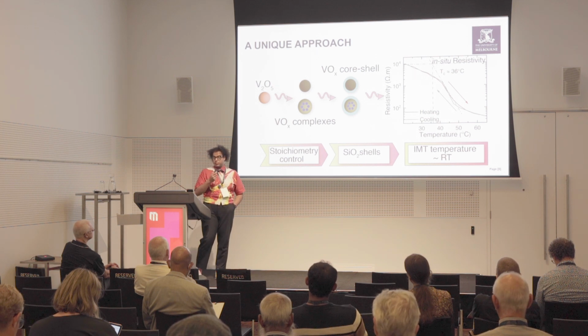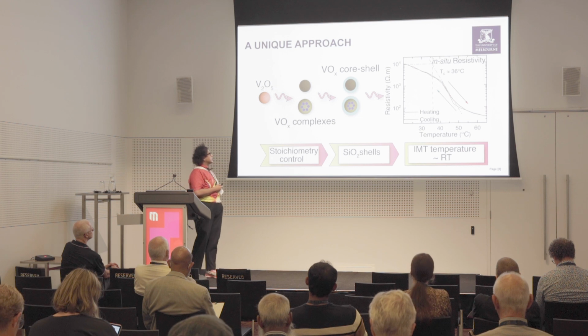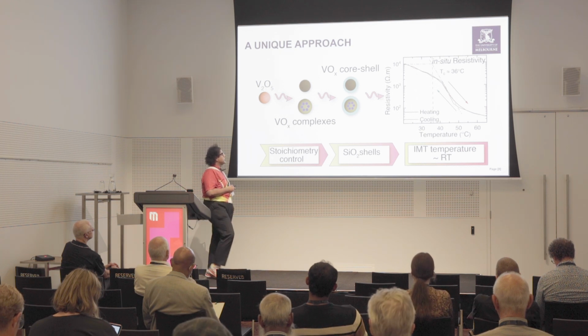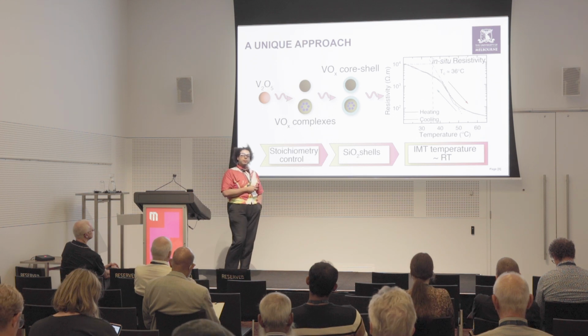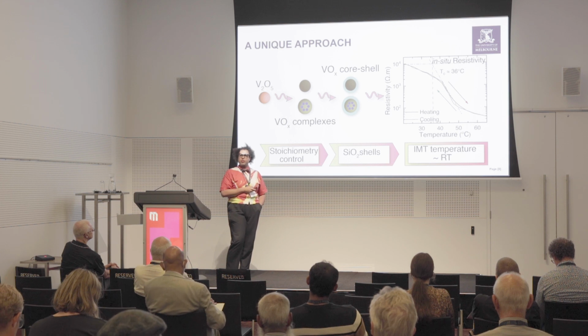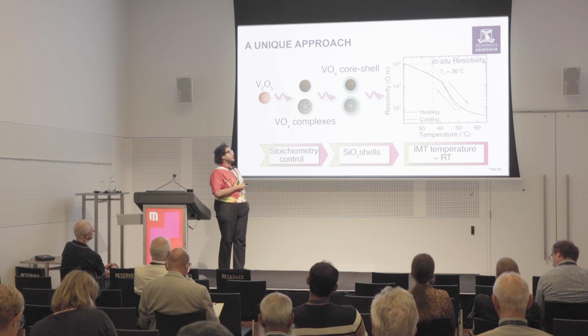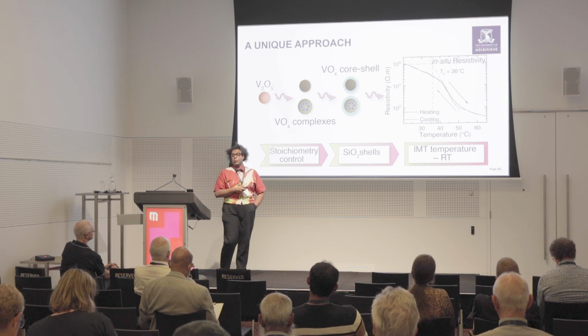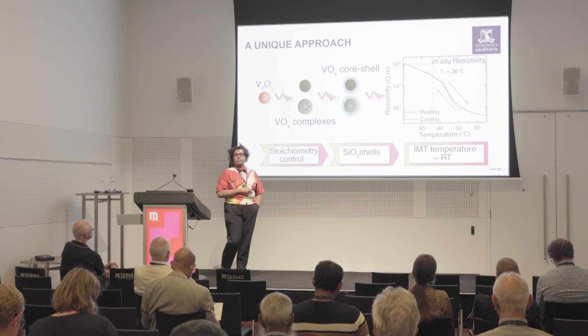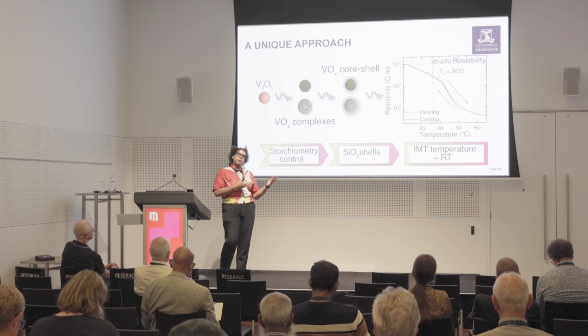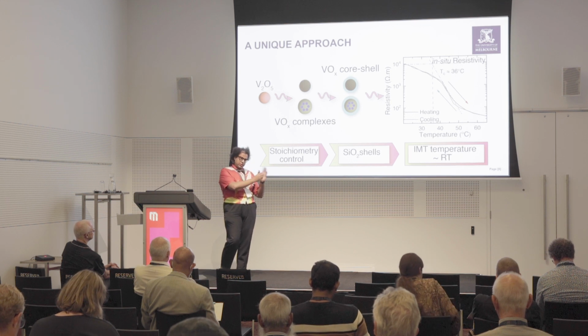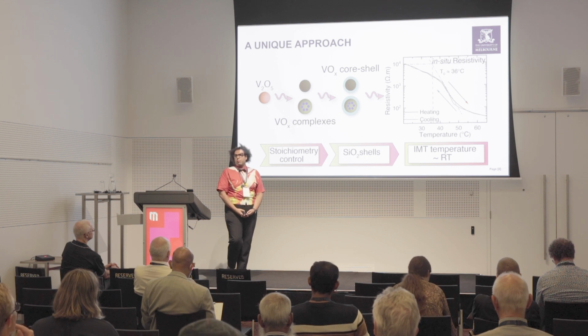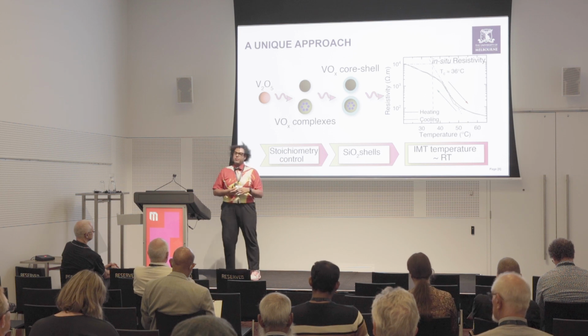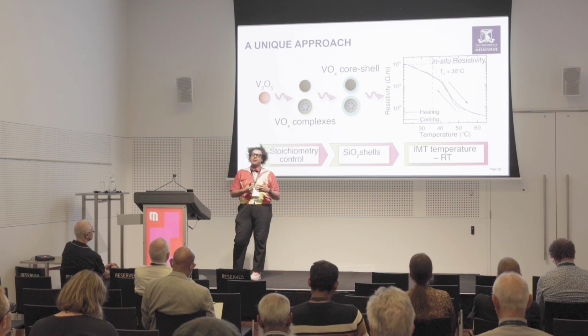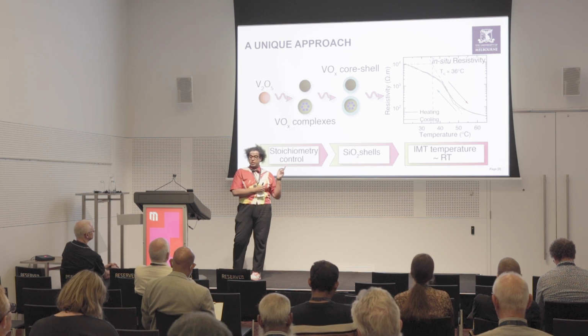What we did in our work is we created a system with which we can make vanadium oxide nanoparticles that work around room temperature, because undisturbed vanadium oxide only starts to switch around 68 degrees, but through our work, we're able to push it down all the way to 36 degrees. It's a big deal because we don't use any dopants, we don't add any extra shenanigans to the compound, because normally people add tungsten, other metals to shift and move it closer. So basically, the status quo for changing that transition temperature is adding more metal, to physically make it more metallic. So they add tungsten, they add molybdenum and other compounds to shift that transition.